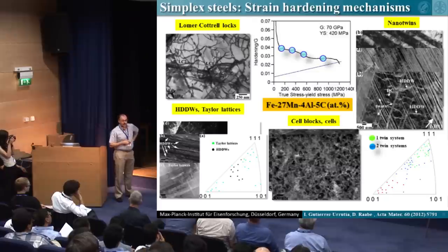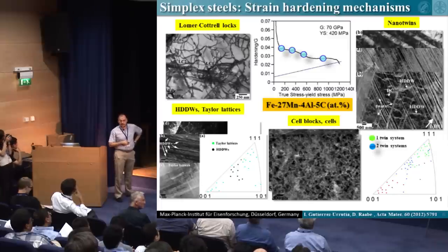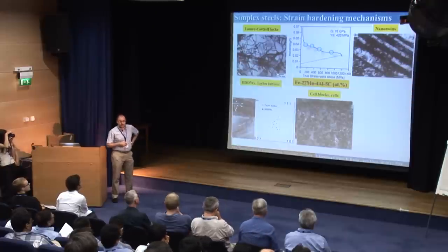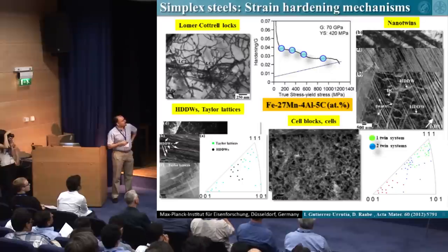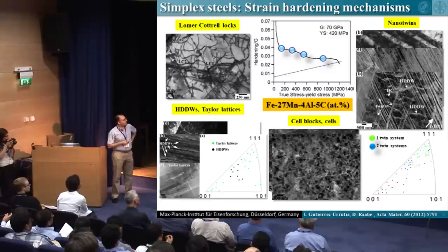So this is the deformation structure in the first stage of hardening. And as soon as twinning is active, we promote the formation of nanotwins. In order to characterize the thickness of all these features, be careful, we only have to place the planes of these interfaces edge on. As you can see here, these are FCC materials, so the nanotwins are formed and distributed into bundles. And as you can see, we have a distribution in thickness. So fine, up to 10 nanometers, but we can easily go up to 50 nanometers or even 100 nanometers.